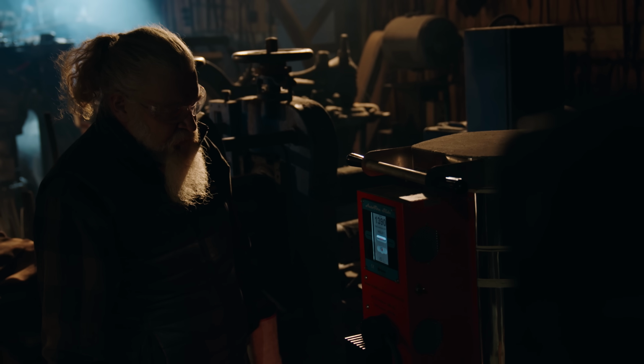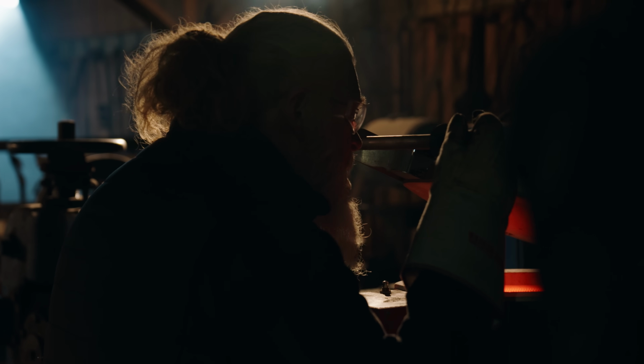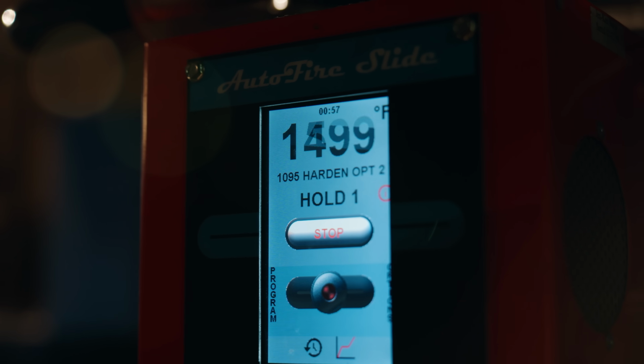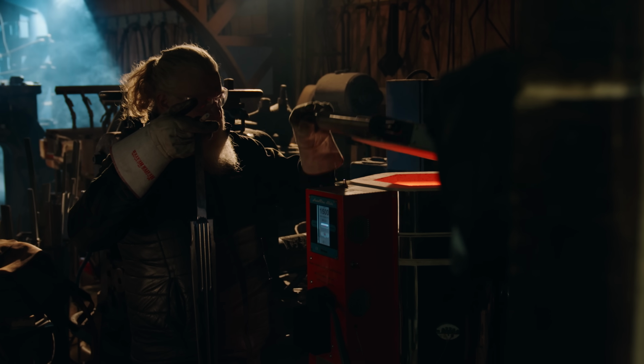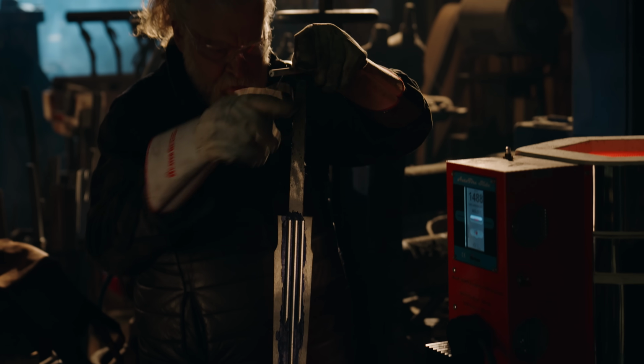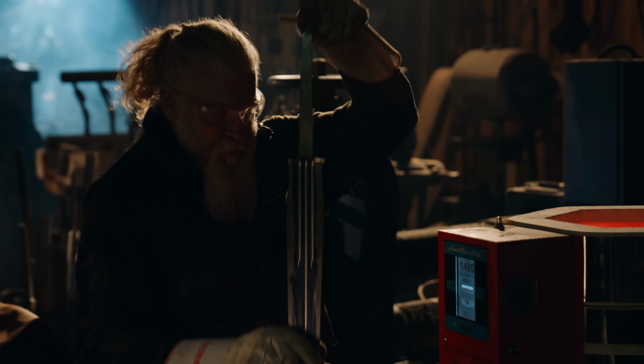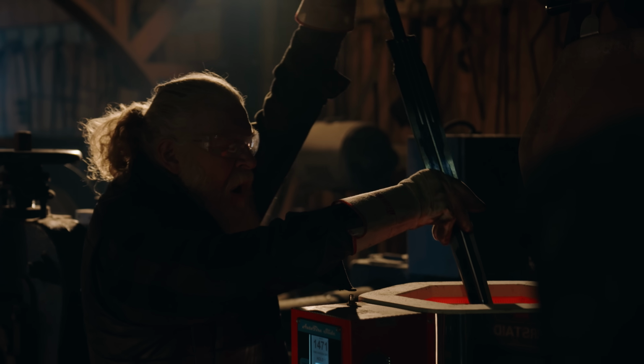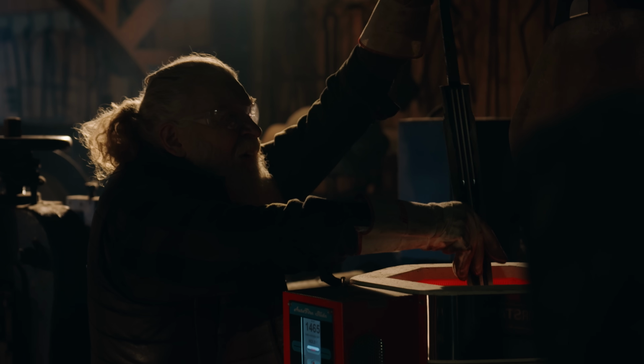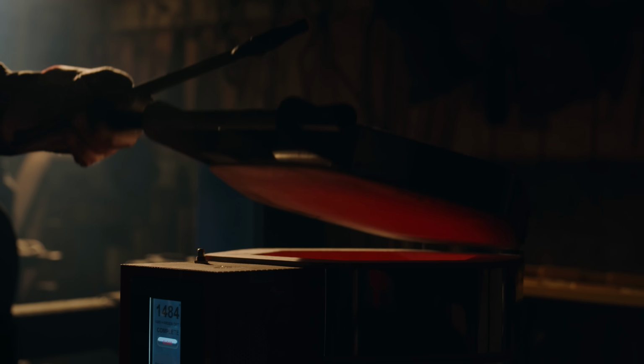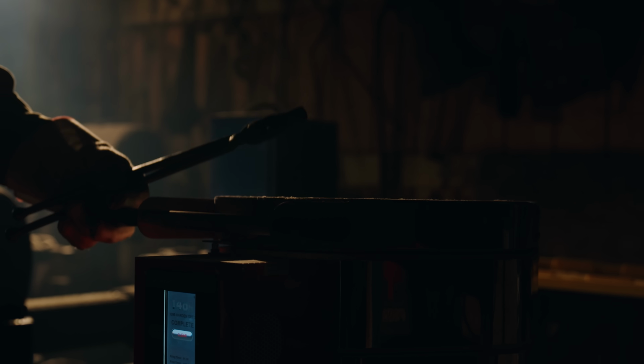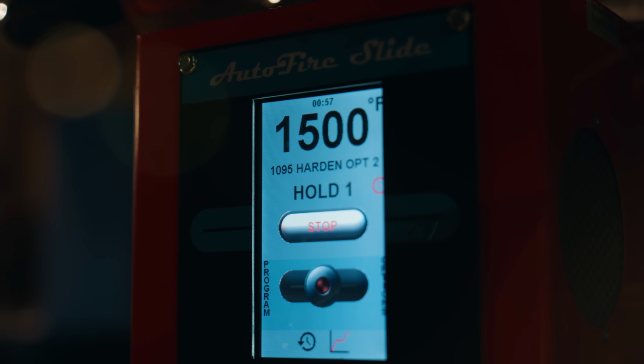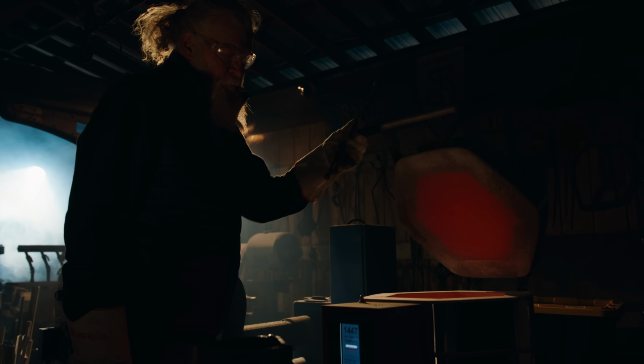For heat treating, we put the blade into the kiln at 1500 degrees and allow it to soak for half an hour. We then withdraw it and quench it into Parks 50 quenching oil. After that, it's going to go over to one of the other big kilns and sit at 400 degrees for 2 hours on 2 processes. That's going to bring it back and be something that's very resilient, and we won't have to worry about breaking.